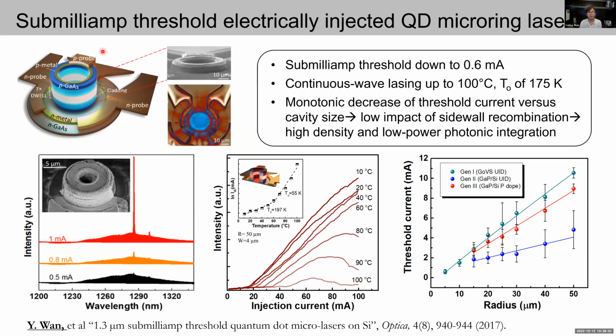Compared to optical pumping, electrical injection of micro lasers is more challenging because the electrode metallization is limited by the micro-sized cavity. Here we have a special etching recipe and a sidewall passivation technique so that we can form this 4 micron mesa with a straight etching profile and a smooth sidewall surface. So the electrically injected microring can have a sub-milliamp threshold and a maximum operation temperature up to 100 degrees C and a characteristic temperature as high as 175 Kelvin.